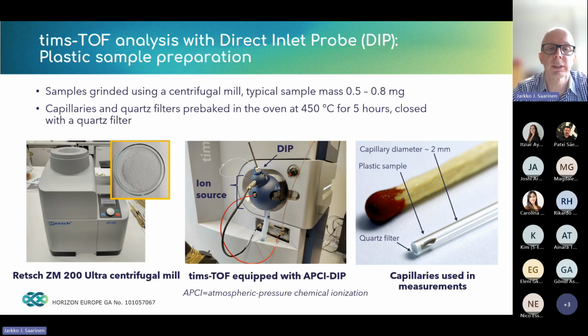Here on the left-hand side, you can see the typical glass capillaries that are used for the direct inlet probe. We apply a quartz filter at the end of the capillary to prevent the samples from being immediately ejected from the capillary. Then this is applied into the ion source, and the sample is ionized and analyzed. So very small amounts of sample can be used. In this picture, we can also use material from a plastic sample that is simply a piece of plastic fitted into the quartz filter. You can see the size of the capillary compared to the matchstick in this image. Once it's embedded into the direct inlet probe, it's ionized, and then we analyze it using our timsTOF device.